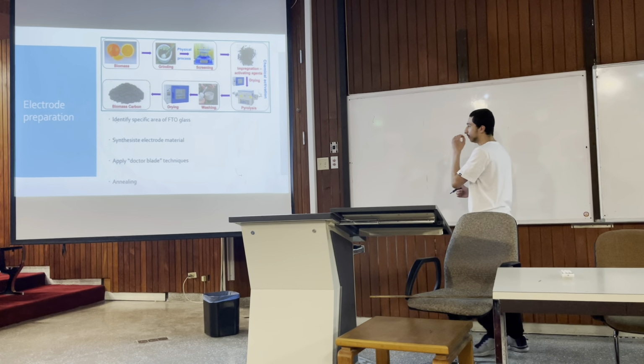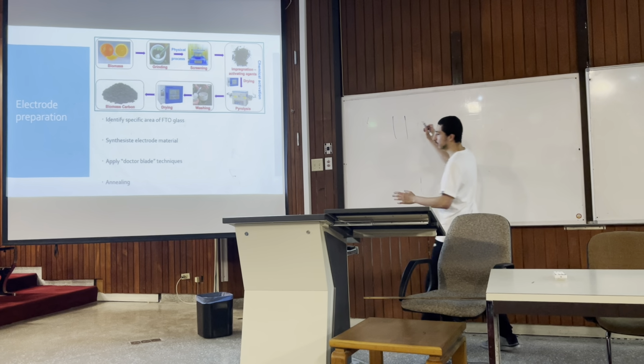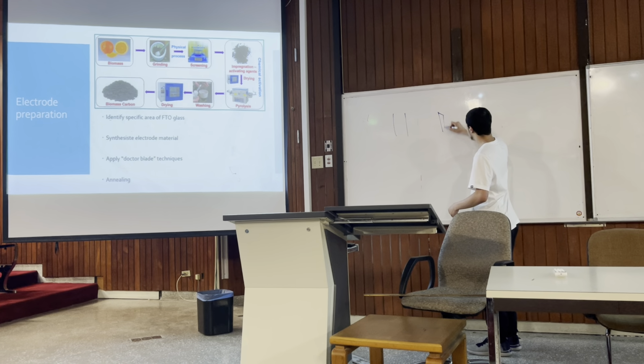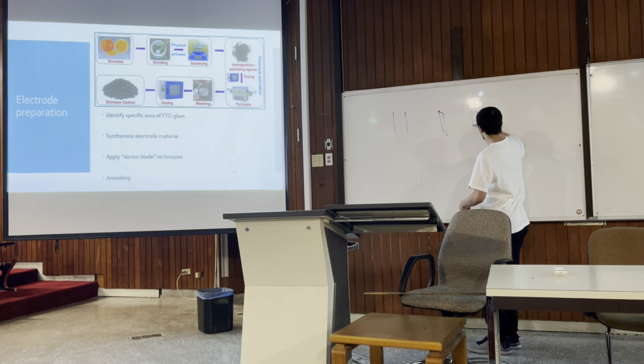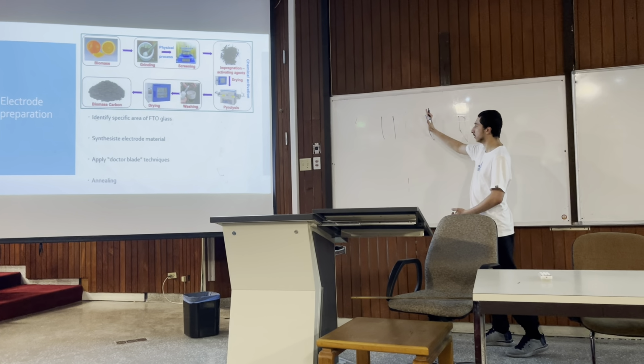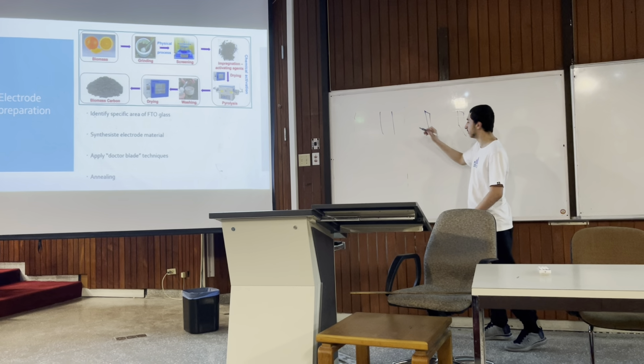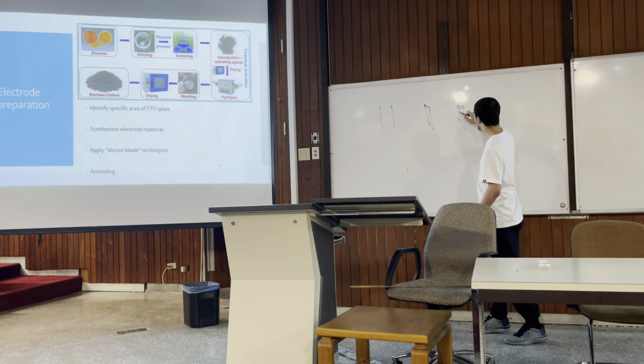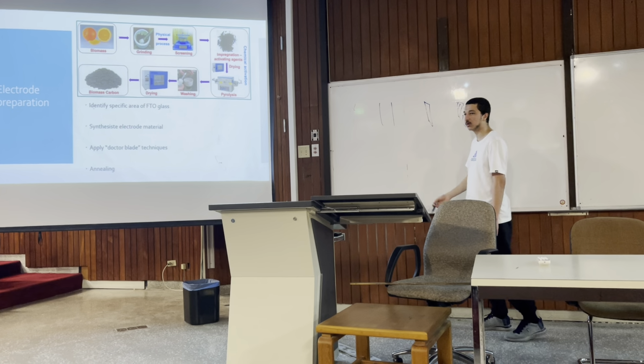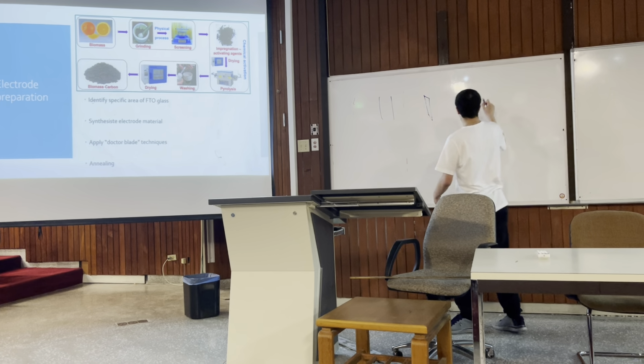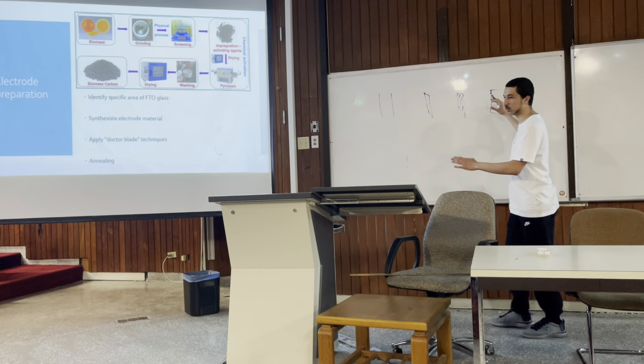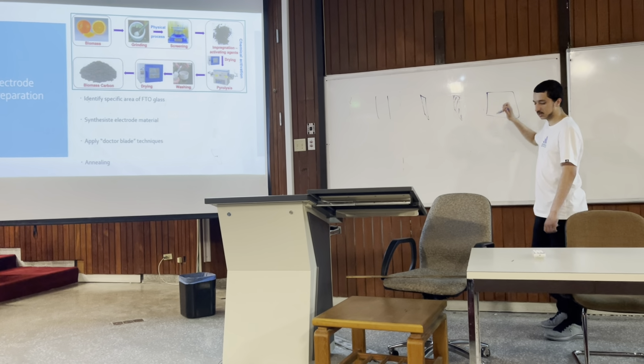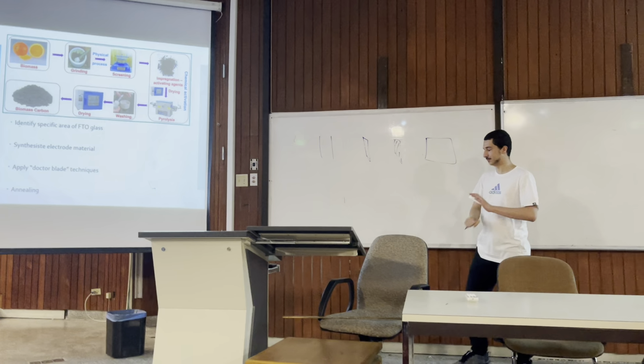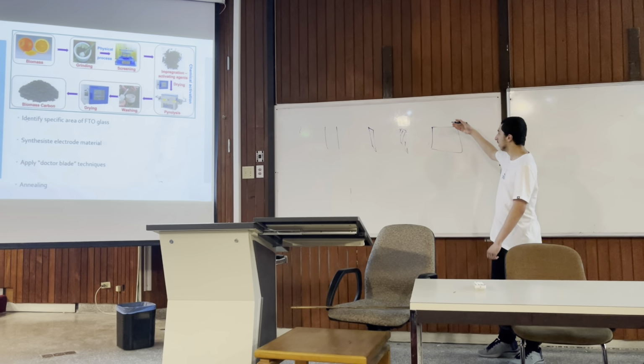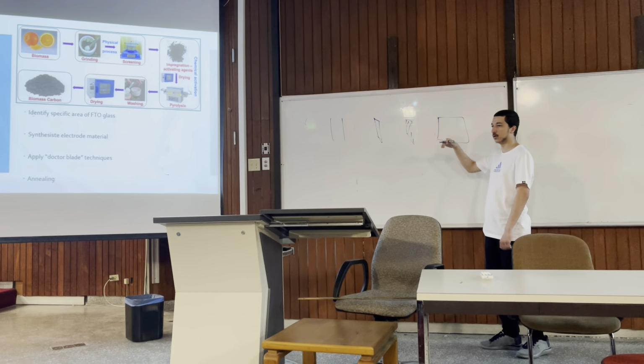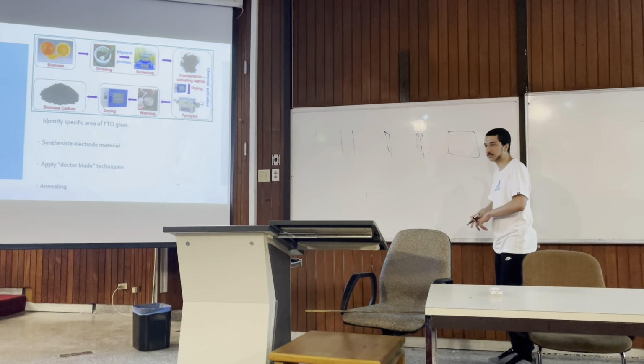So, we know the supercapacitor has 2 plates. If we imagine them to be 3D plates, having carbon on the whole thing would take a lot of material, and we're still at the research stage. So we don't make a full carbon electrode. What we have is FTO glass, which is fluorine-doped tin oxide. It's almost like activated glass. It's very popular. You use it to grow thin films, and for fabrication processes.